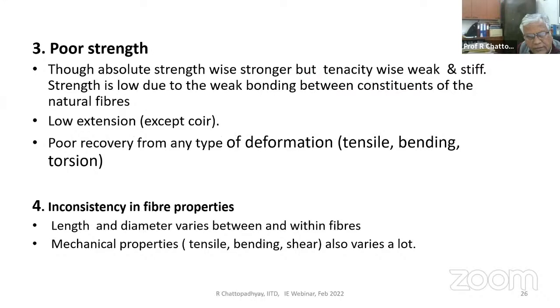Poor strength, as we have already discussed: when you compare the strength of natural fibers or plant fibers with the synthetic ones, high performance fibers, then you see strength is much less in the case of natural fibers. It has a lower extension and poor recovery from any type of deformation, tensile, bending, or torsion. That means the fibers are not really very elastic in nature. There will be permanent deformation if there is a severe stress that acts on it. These are some of the weaknesses, and inconsistency in the properties. The length and diameter vary a lot, as we have already said, and mechanical properties also vary a lot. So these are the weaknesses.